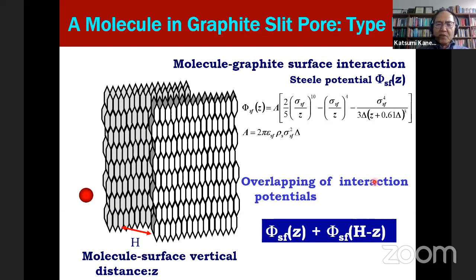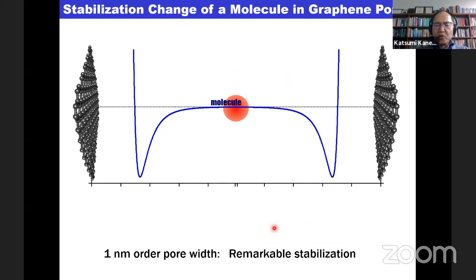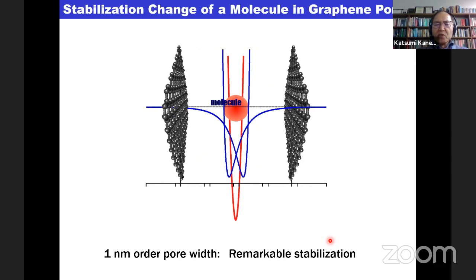Okay, I want to start with the graphite slit pore systems. The molecules enter in the slit shape case. In such a case, the molecule interacts with both the walls, so they have two interaction potentials from both the walls. Then if both walls approach each other, this blue interaction potential overlaps to give the red deep interaction potential. This potential is very, very deep, in some cases corresponding to 3000 kelvins. So very briefly speaking, in order to desorb, heating at 3000 kelvin is necessary. So a very deep interaction potential is produced by the very small pores.